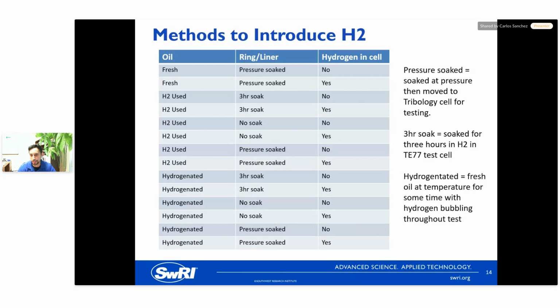So to actually see any sort of effect of hydrogen, you really need to basically soak it in hydrogen. And by that, I mean have the parts sitting in the chamber fully flooded with hydrogen for, in this case, 3 hours. We did several different time frames for this, up to even 24 and 48 hours. We found that within the 3 hour mark seems to be the critical point. So we left it at 3 hours.